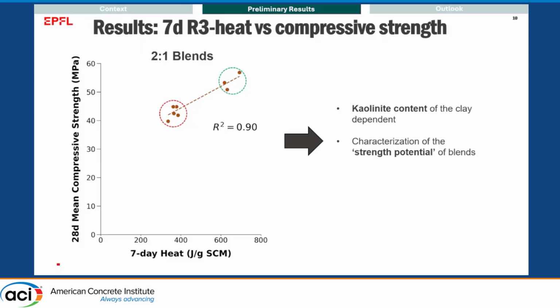So what this means is that, say you have X number of calcined clays and Y number of fillers, and you want to narrow down your options, or your combinations, you can just do 7-day R3 heat, look at the heat signal, and decide if this blend is good enough to give you a good 28-day compressive strength or not. So I think this is really useful in narrowing down your blended options. I would also think of it as a primary screening of blended systems when you have 2:1 blends.